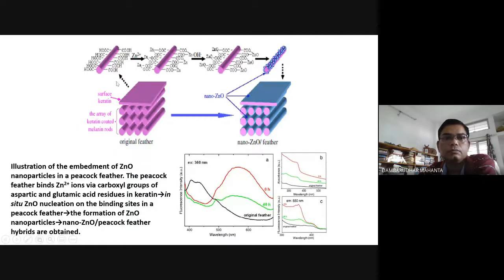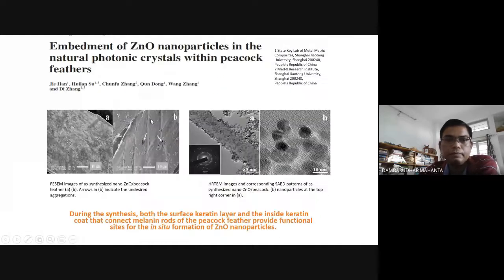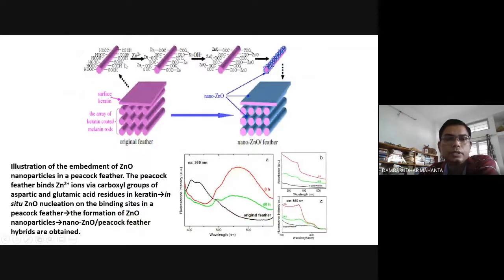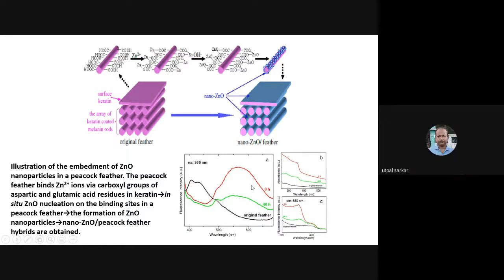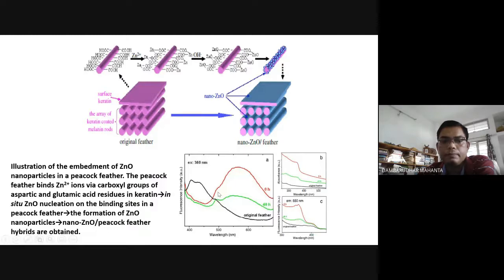Since it is keratin, on the keratin surface you have COOH, etc. So what we did following this article, we have also tried subjecting them to zinc solution, and exchange interaction, so that you can grow particles or nano zinc oxide on this particular melanin rods. So in this reflectance spectra you could see here, this is the original feather, and you have the modified spectra because of zinc oxide loading.